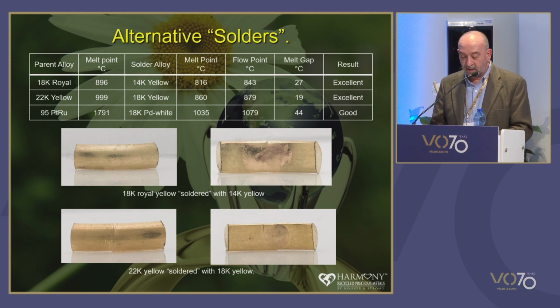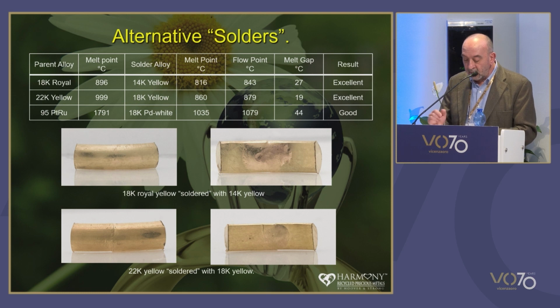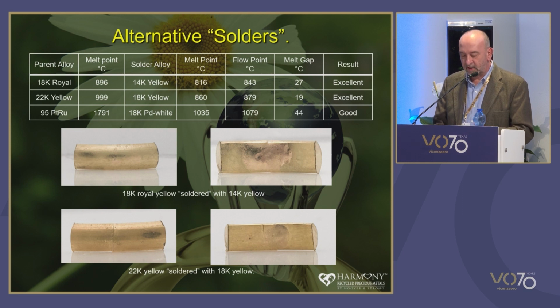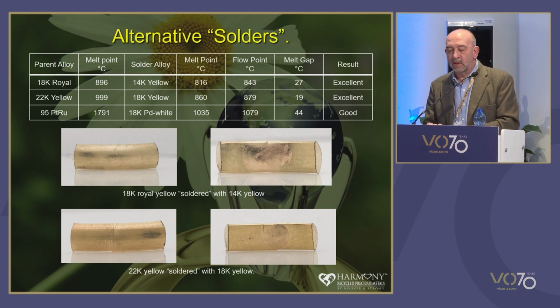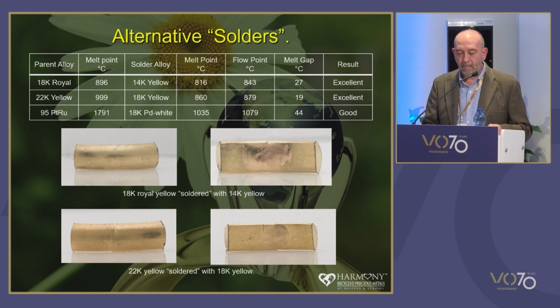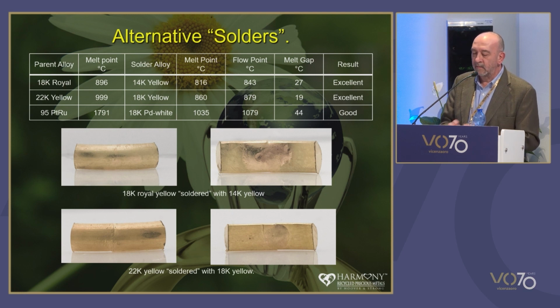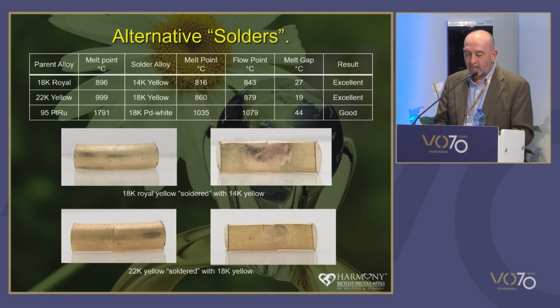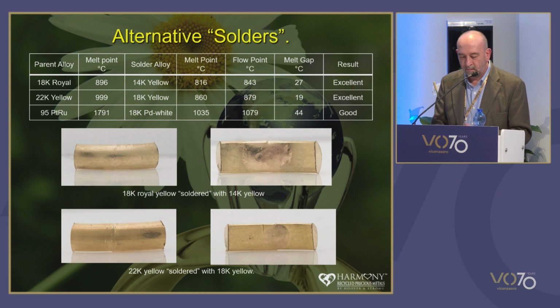And the final observation involved joint geometry. When the joint gap was a good fit, with the flush ring test samples and the ear stud samples, the solders performed satisfactorily. What seems to be clear from these experiments is that when the quality of the joint geometry becomes less than ideal, the solder performance decreases. And based on these tests, it's fair to say that furnace soldering will exacerbate some of these problems.